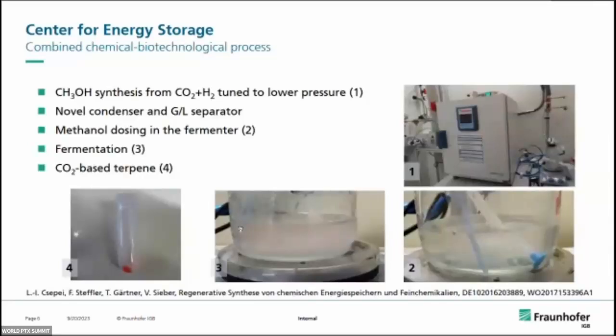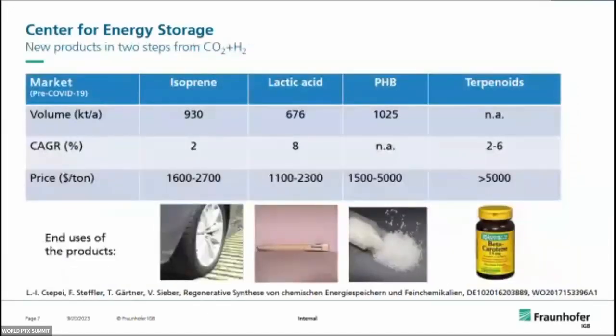Then we further integrated our activities towards process development. That means we combined CO2-based methanol synthesis with further conversion of the methanol, as you can see here. We fermented the methanol into terpene, CO2-based terpene. But terpenes are not the only products. We can also get isoprene, lactic acid, polyhydroxybutyric acid, which is a polymer, or terpenoids in general.